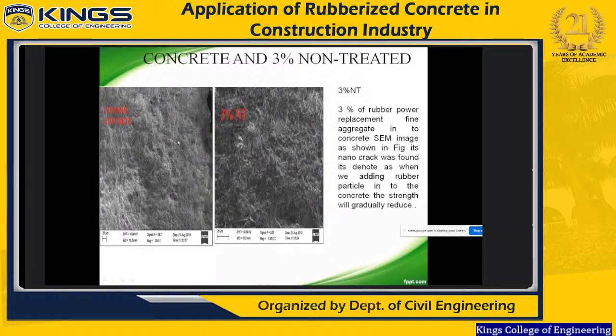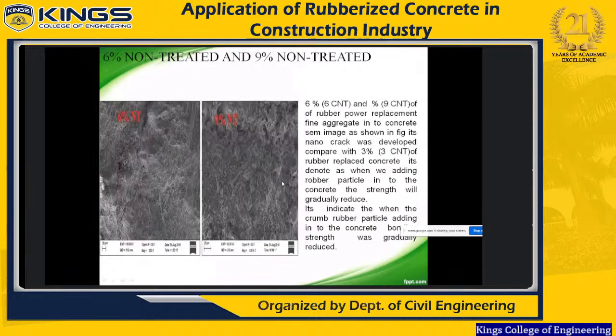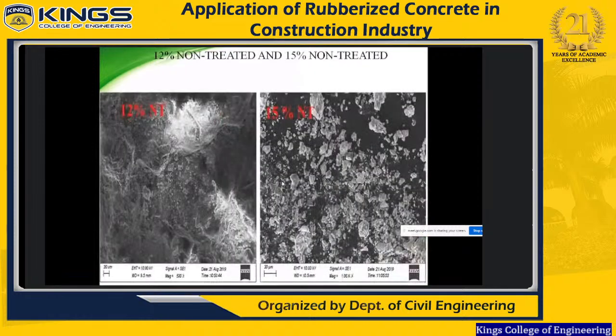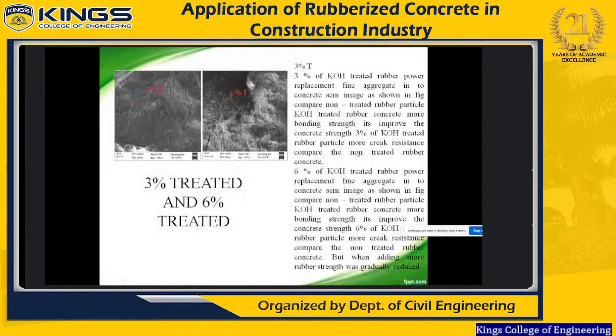In the same way, we have the control concrete and non-treated rubber. What happens with a 3% addition of non-treated rubber in proportion? Some analysis was also carried out. The same for 6%, 9% non-treated rubber, then 12%, and there is a diagram spreading that for 15% non-treated rubber. So it is an SEM analysis.